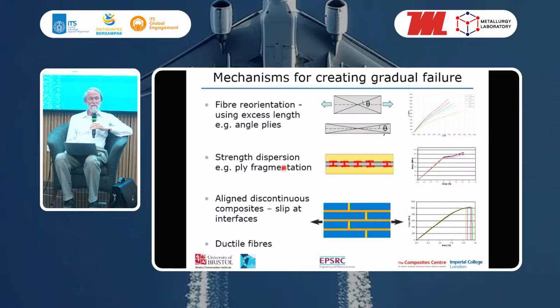The second main way we looked at was by using strength dispersion. So rather than having one material which fails at the same strain, we have different materials which fail over a range of different strains. One of the main ways of doing that was with these hybrid composites, whereby we use two different materials and we get this fragmentation. So that's what I'm going to be talking about today.